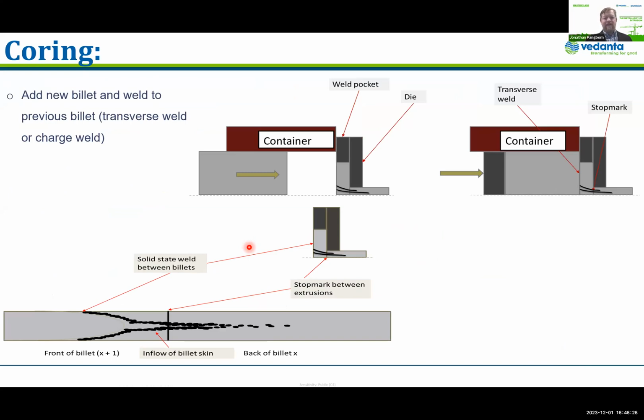By cutting that butt off, in addition to the pressure buildup and so forth that we can't have for pushing to a paper thin butt, we're purposely removing the majority of this. But in this example here, a weld pocket and a stop mark on the extrusion, anything that goes actually into the extrusion will be in the billet that was pushed. Anything that is remaining in the die, you won't see. You'll see it on the other side of the stop mark on what we would call the second billet, the billet following, but is actually still cleaning out in front of the transverse weld some of that.